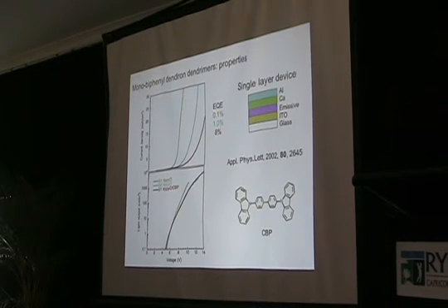In terms of green, for the small molecule ones with these great numbers of layers and different materials, people have basically got 20%. The best we've got is 16%, but in much simpler device structures. Instead of generally 5 layers and 6 materials, we can get 16% out of 2 layers and 3 materials. So from a manufacturing point of view, it's much simpler. In fact, we've had 13% out of 2 layers and 2 materials. So by careful design of your materials, you can make the manufacturing process a bit simpler.